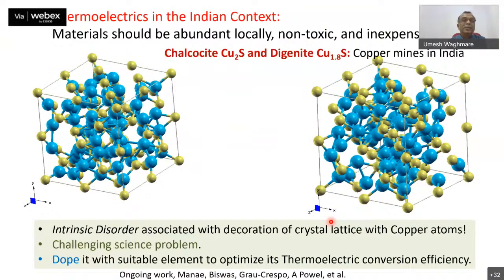So now we are using this scheme in the Indian context, where the materials we are focused on are chalcocite, which is the sulfide of copper, and digenite, which is a copper-deficient sulfide of copper. These two are intrinsically disordered because copper atoms have too many sites in the crystal available to occupy for the number of copper atoms. So this site occupancy disorder attracted us to the science of these materials, and also the fact that they are non-toxic, abundant locally, and inexpensive.